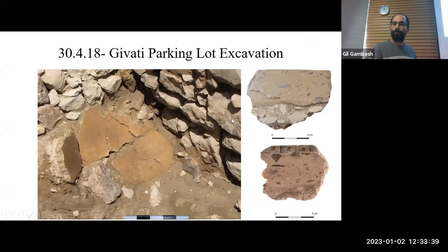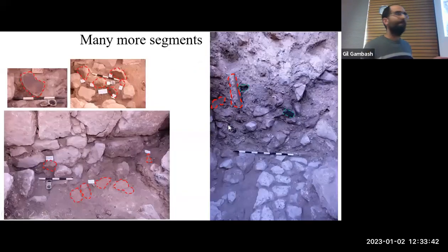So when they excavated, they found a 2 meter wide destruction layer full of debris. You can see it over here, and within this there were many more segments of this surface. You can see one here, almost completely vertical, and one here with a lot of charcoal and burnt material around it. And some of them were lying on the floor of the bottom story of this monumental building, and you can see one here, vertical. There were probably hundreds of these segments, and I didn't sample all of them, but I sampled the bigger ones.